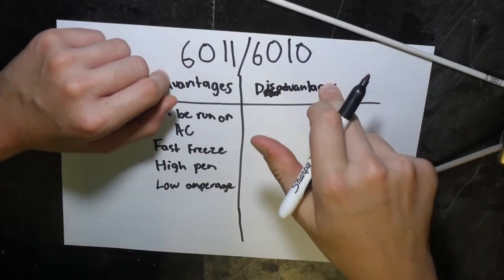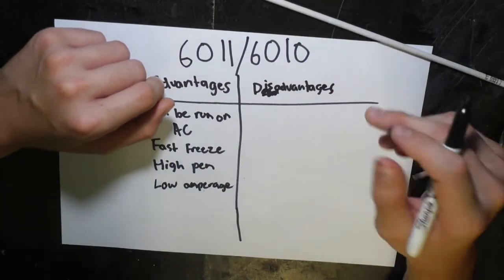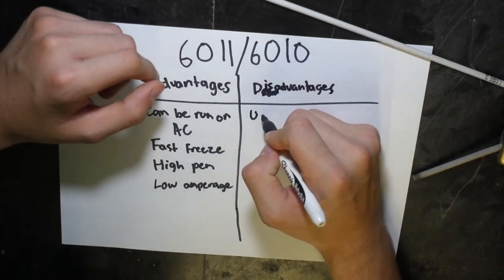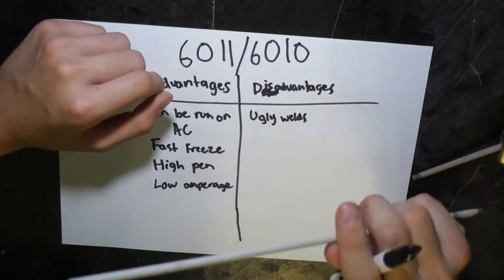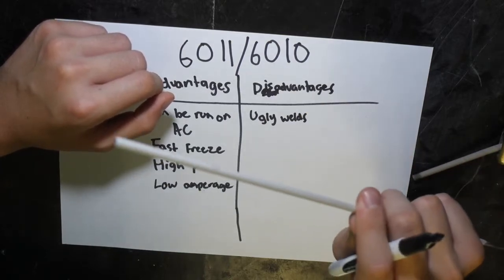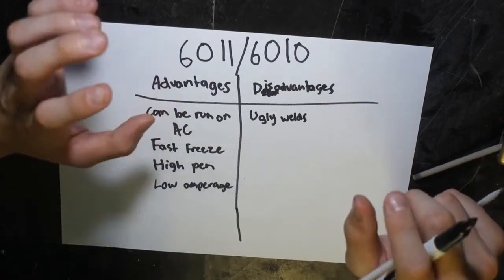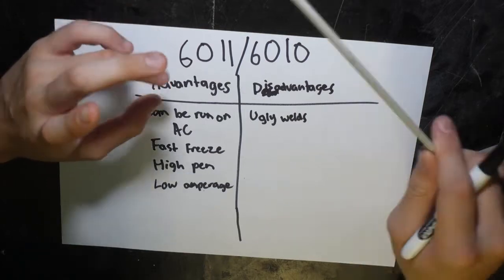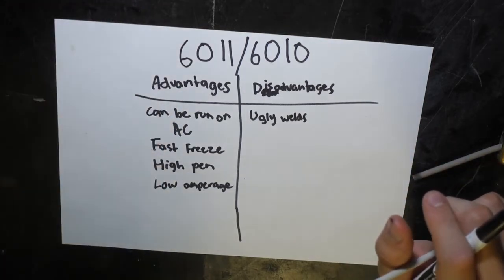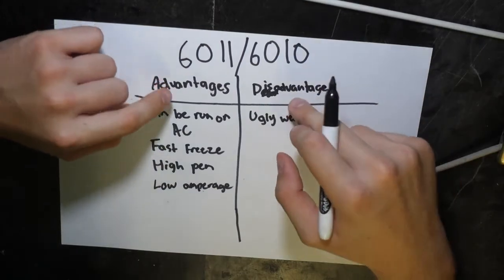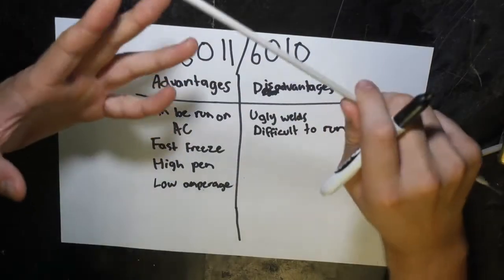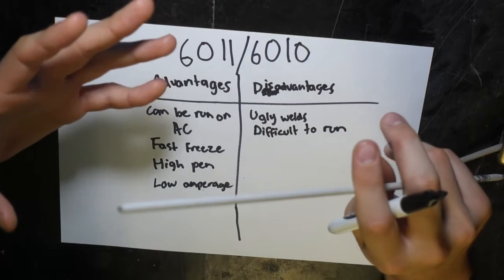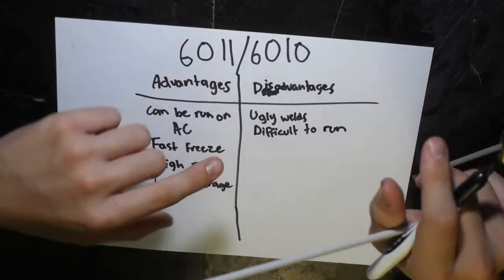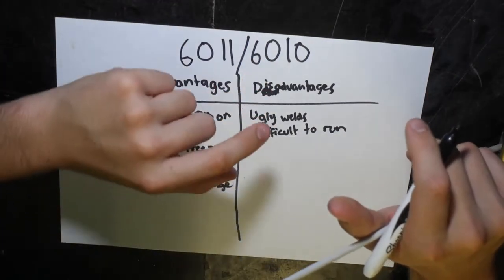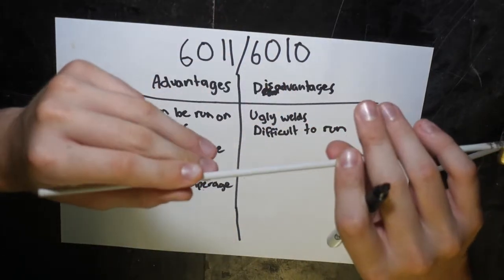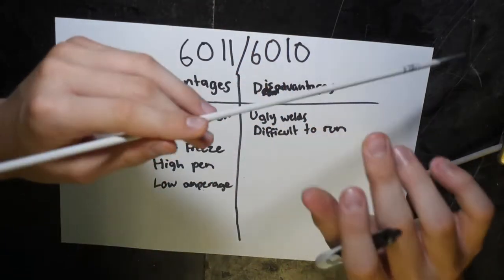Disadvantages, here's where we really see the downfall of 6010 and 6011. Ugly welds. 6010 and 6011, because they freeze fast, every little motion you make creates an indent and you'll be able to see it in the final weld. These rods can be difficult to run. In fact, most moderately priced welding machines struggle quite a bit with 6010. This is why so many people use 6011 on DC welding machines.